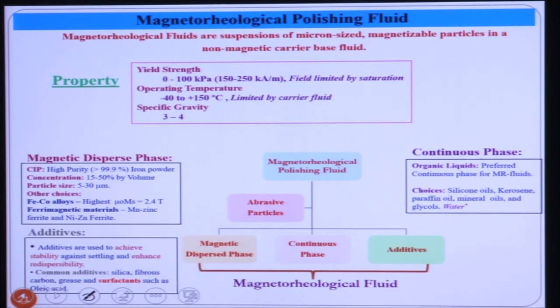First, we prepare the base media, which consists of paraffin oil and a grease additive. We start with 80 percent by weight of paraffin oil and 20 percent by weight of the grease additive, then mix it homogeneously for several hours to make a homogeneous mixture.